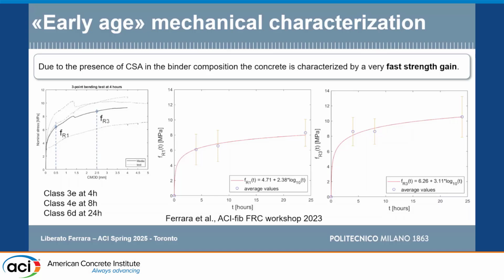And the letter, E or D, in the case that we are working on, are requirements for the applications where you want to eliminate the conventional reinforcement. E means that the ratio between this stress here at 2.5 millimeter and this stress here at 0.5 millimeter is higher than 1.3. And class D means that that ratio is between 1.1 and 1.3. So you must have a very stable and reliable deflection hardening response. Deflection hardening does not mean that the material is strain hardening, because you have to go from flexural response to direct tension through back analysis, and you have some factors there.